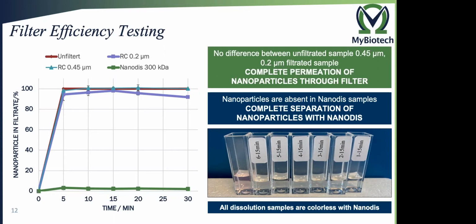If you try to filtrate with 0.2 micrometer filter, there is a very slight decrease in the dissolution, which is due to the fact that there was a very small part of the nanoparticles which were slightly higher than 0.2 micrometers, so these are filtered out of the medium, but every other particle goes through. But when we try it with the Nanodis, we have seen that we don't have any particles in the dissolution medium, which shows us that we have a complete filtration of the nanoparticles from the dissolution medium using Nanodis.